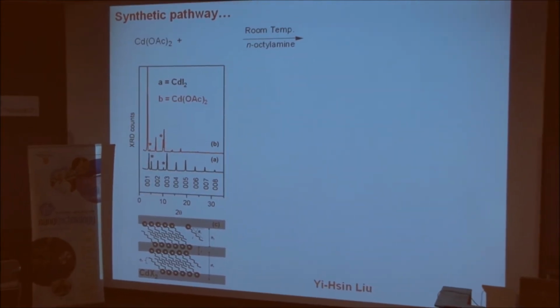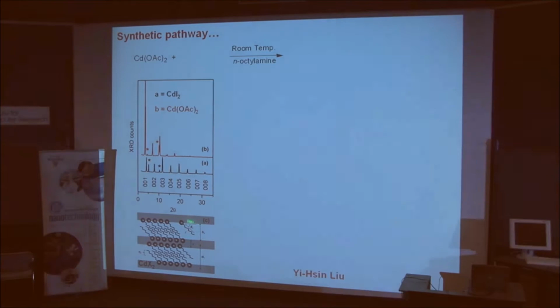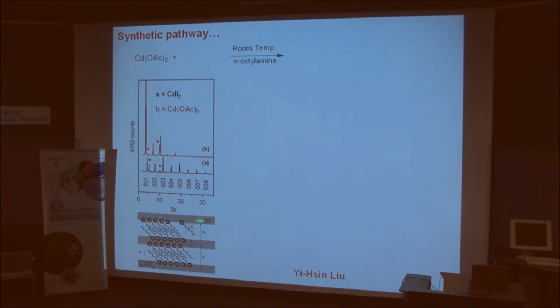It exhibits a series of low-angle reflections that are normally associated with a lamellar structure. In fact, what has happened is the precursor has formed a lamellar-like structure in which there are layers of cadmium acetate separated by amine bilayers, where the amine head groups are bound to the cadmium acetate layers. We can reproduce exactly this phenomenon in a cadmium compound that's very well known to have a layered structure, cadmium iodide, which I show you here. So the first thing that we form is a template structure with lamellar galleries of cadmium acetate precursor separated by amine bilayers.